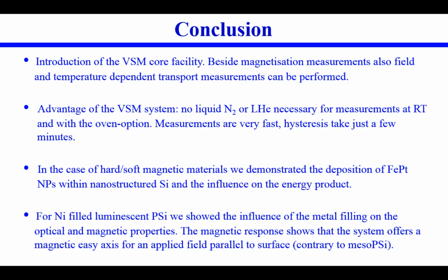In the case of hard soft magnetic materials, I showed you the deposition of iron platinum particles within nanostructured silicon and the influence on the energy product. And for nickel-filled luminescent porous silicon, I showed the influence of the metal filling on the optical and magnetic properties. The magnetic response shows that the system offers a magnetic easy axis for an applied field parallel to the surface, and this is in contrast to mesoporous silicon.